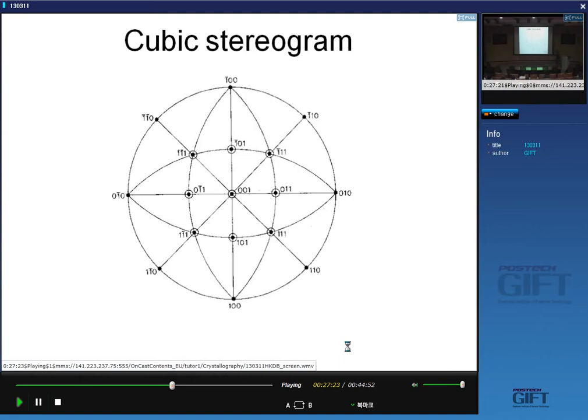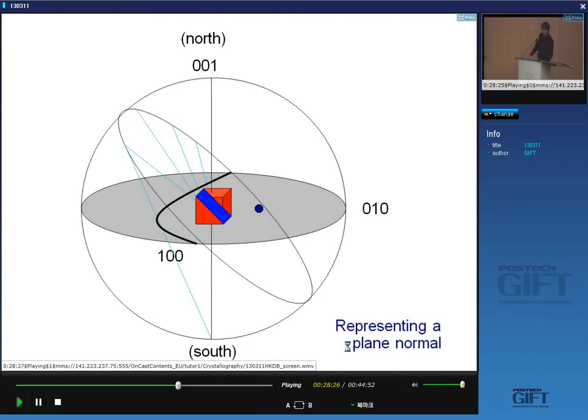Similarly, this is the 101 plane, and this is the trace of the 101 plane, and everything on this trace is at 90 degrees to this. So for example, if I take a dot product between 101 and bar 101, that's also zero, because 1 times minus 1 plus 1 times 1 is zero. Similarly, if I take a dot product of bar 1, bar 11 with 101, it's also zero. So this is the trace of the 101 plane. This is the 110 plane, and all points on here are at 90 degrees because the 110 plane is cutting vertically through this diagram along there. So the trace of a plane is at 90 degrees to the pole. Okay, so that's the pole and that's the trace.